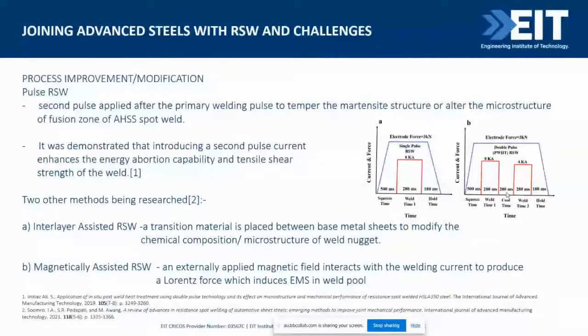All right, by using double pulse, or even some use triple pulse, the whole idea here is to soften the spot weld. That means to reduce the intensity of the martensite. Now with that, it was found that we can still spot weld the AHSS materials easily, even though naturally they are quite brittle. But with the use of a multi-pulse, we can easily weld all the various types of AHSS we've got. We've got the DPs, we've got the CPs, and so on, which can be welded easily. Right?